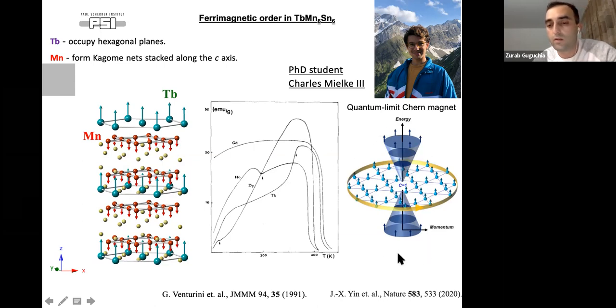And the group of Zahid Hasan identified this system as a new topological magnet. So what does this mean? I'll just list some observations that were reported in this 2020 paper. They see quantum oscillations from relatively low fields of about 7 Tesla, which reveal the Landau quantization. And by analyzing this Landau fan structure, they found a spin polarized Dirac dispersion and a large Chern gap in this system. They also find a large anomalous Hall conductivity that comes from the Berry curvature fields, and also a quasi-linear magnetoresistance that was explained to come from the linearly dispersive, polarized bands.